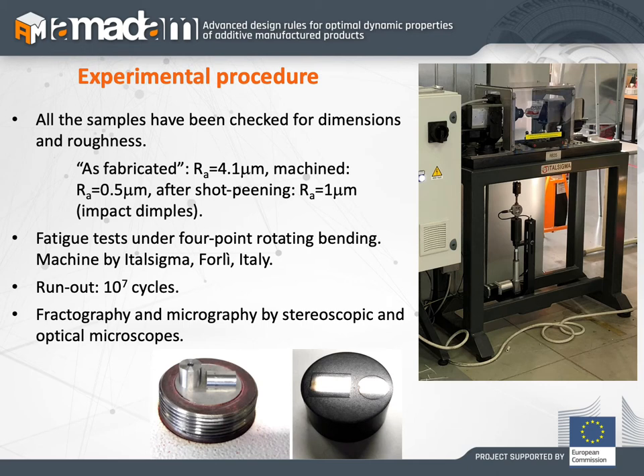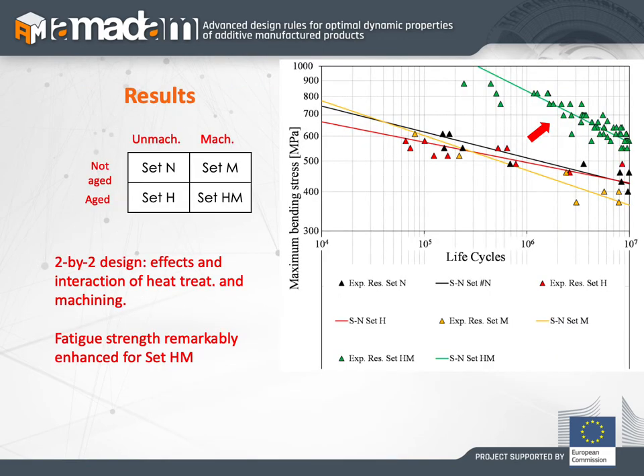So there is a controversial situation in considering whether the specimen could reach a lower or higher level of fatigue resistance in such a situation. The runout was set at 10 to the 7 cycles. Okay, here we have the S-N curves, the results plotted. As you can see, the different lines with different colors represent the different sets of specimens, and particularly the HM set has significance in modifying the S-N curves, and particularly the fatigue limit.